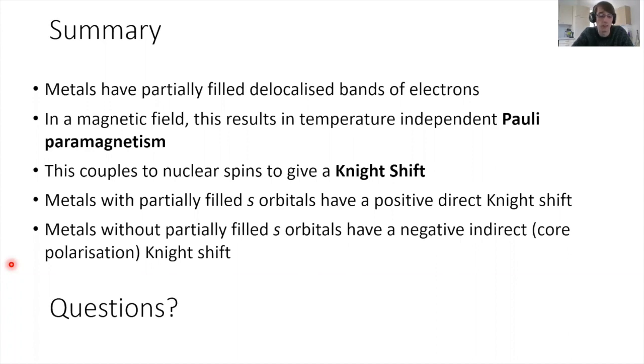Fermi contact is the main interaction which actually gives you a shift. The Fermi contact interaction is isotropic. So in order to get an anisotropic Knight shift in that case, you would require an anisotropic susceptibility, which can be the case, especially if you have more complicated band structures.